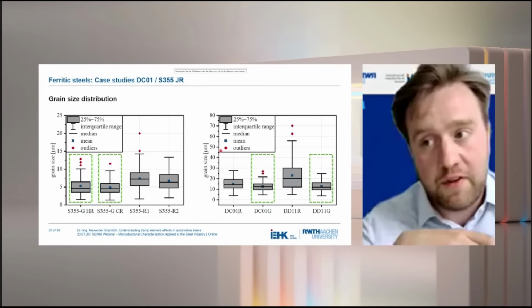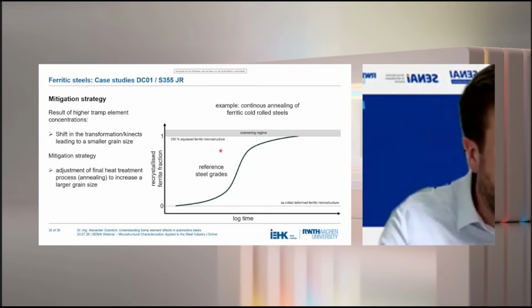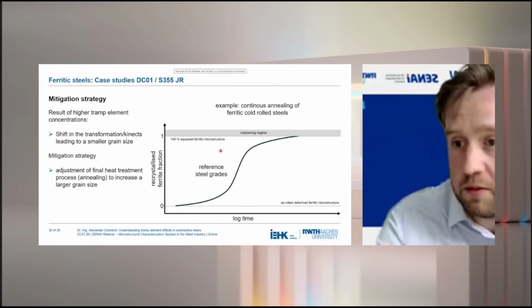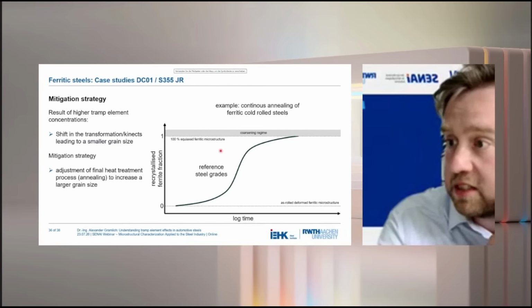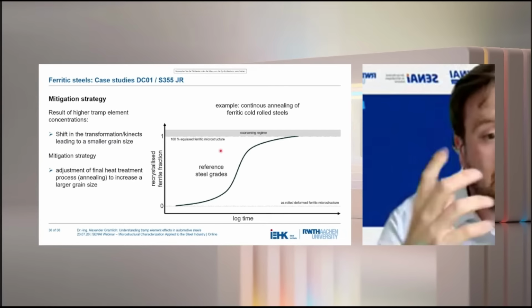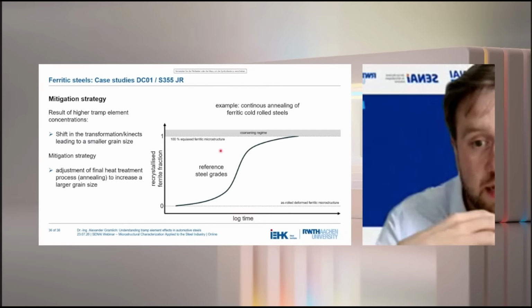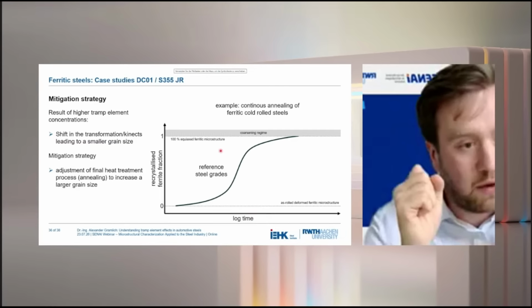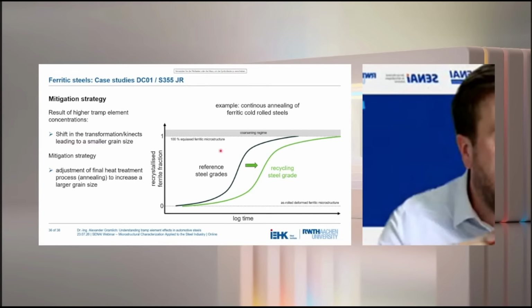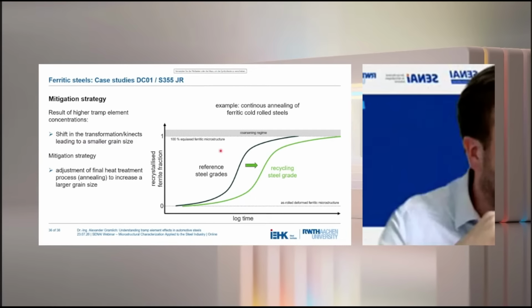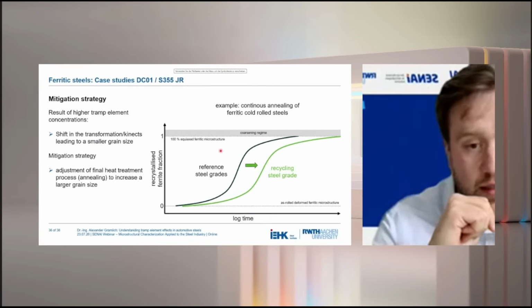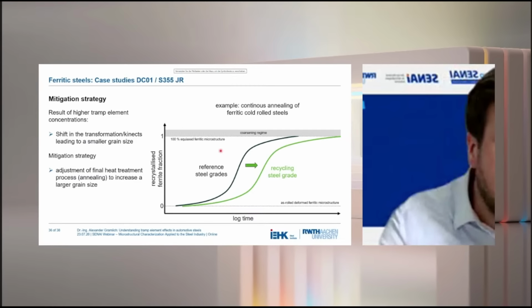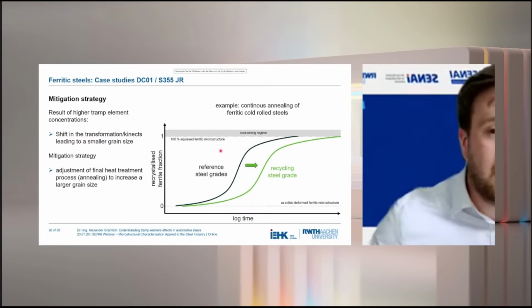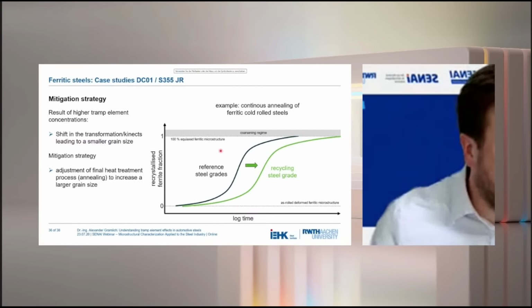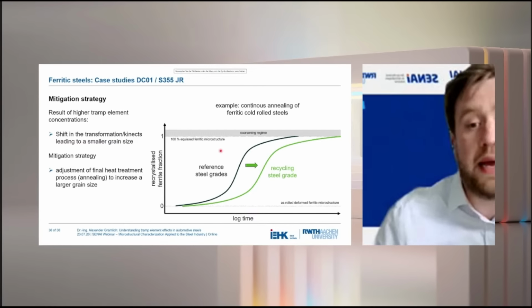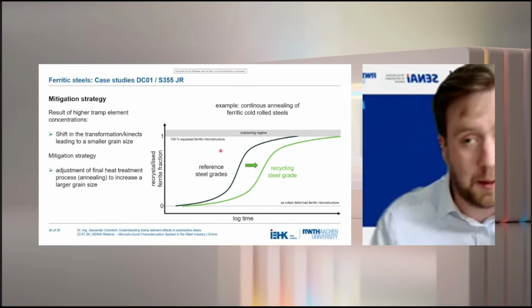This also fits very nicely back to the beginning of the talk. Here you are seeing now basically a more schematized drawing of the recrystallized ferrite fraction in our steel grades, and what is basically happening when we add tramp elements. So when we are looking at recycled steel grades, this recrystallization is shifted to longer times, and this can be assessed, and we can work against this by adapting process parameters, for example.